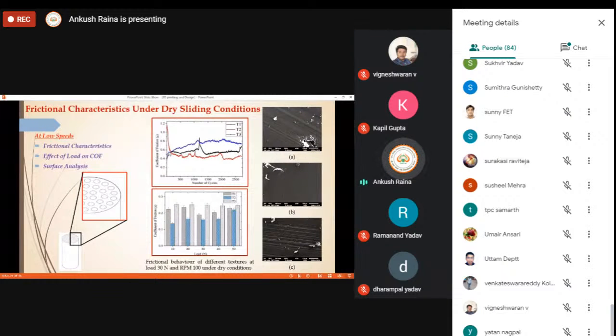So for texture T3, the coefficient of friction increases till 1000 number of cycles, and then it tends to stabilize. Also, there is no abrupt breakup. Generally, if there is an abrupt peak, which is the case in the black curve, it certainly means that there is some resistance which has occurred due to some foreign particles or wear debris. But in texture T3, there is no abrupt peak, and after 1000 cycles you can see there is not much change in the coefficient of friction. It is somewhat in a stable range.